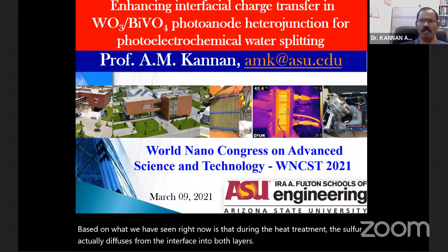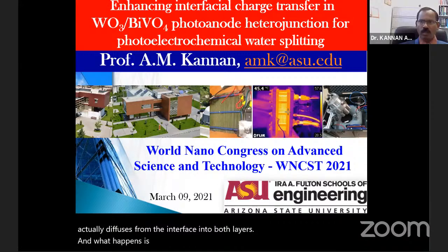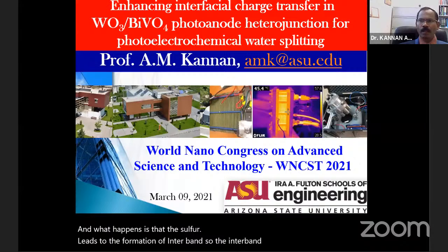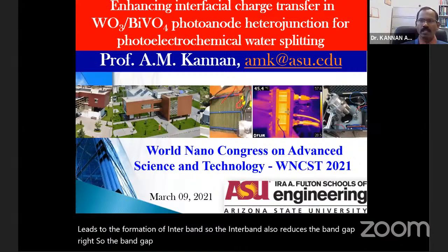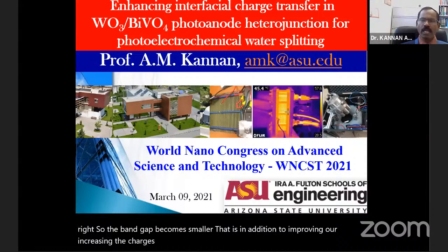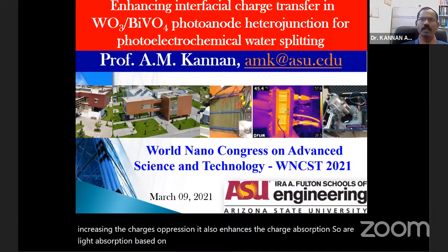The sulfur leads to the formation of an interband, which also reduces the band gap, right? So the band gap becomes smaller. In addition to increasing the charge separation, it also enhances light absorption based on the change in the band gap.